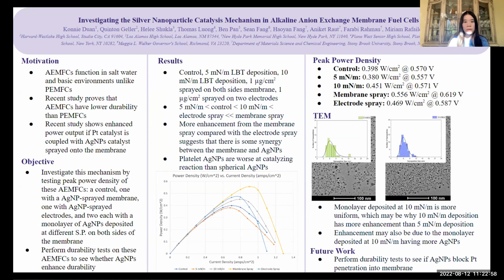sprayed onto the membrane. Our objective is to better understand the silver nanoparticle catalysis mechanism by studying the effect of when we deposit a monolayer of it through an LBT at different surface pressures versus when we spray it directly onto the membranes and electrodes of the AEMFC. We also wish to perform a durability test to see if the silver nanoparticles provide any special enhancement on the AEMFCs there as well.